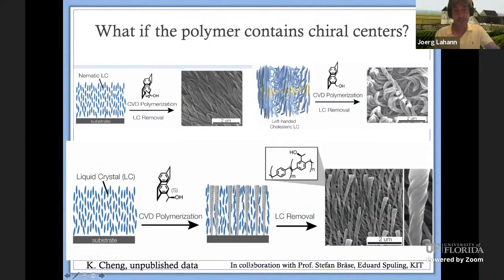So if we just do the nematic phase and basically a molecule that lacks central chirality, then we get straight fibers here. If we do the same thing with the chiral LC, we get this kind of swirling fibers. They're not really helices, I would say. They're kind of swirling because of the very large pitch that exists in those cholesteric LCs. Now, if we use a molecule like this that actually has a chiral center here and use a nematic phase, what we get is now these nanohelices that have very, very high pitches on the order of hundreds of nanometers.